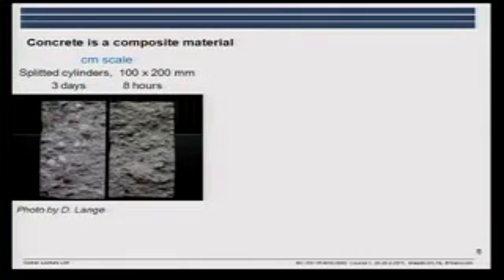When we're talking about cementitious materials, concrete or mortar or cement paste, we have to consider the range we're looking at. And concrete is a composite material at different levels also. We have the centimeter scale. Here we have split cylinders of concrete, and they have hydrated for different times. They're very young, where we see that the fracture has taken place in the paste. You can nearly see no aggregates here. And then 3 days old, where we see that the paste has become stronger, and we have also fracture in the aggregates. You see the red and black aggregates here, white.